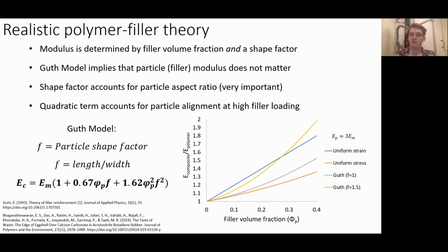And we can see that in the graph I've made here on the right of the 2 idealistic theories and the Guth model. And we can see with that quadratic term as well, as your volume fraction of your filler gets larger and larger, this quadratic term accounts for particle alignment at high filler loading, which states that as you increase your filler volume fraction, the particles are going to start interacting with each other rather than just with the polymer. And this results in a pretty sharp increase in your Young's modulus. And so this is the model that almost everyone has adopted for polymer filler composites, and it's the model we'll be looking at today.